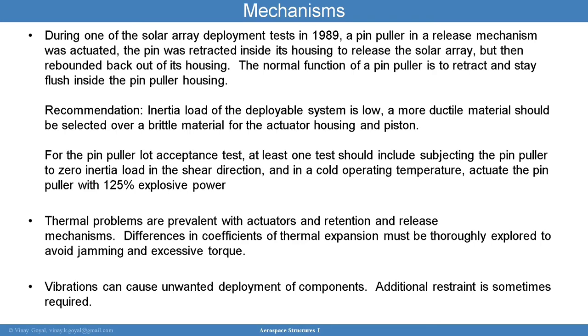During one of the solar array deployment tests in 1989, a pin puller in a release mechanism was actuated. The pin was retracted inside its housing to release the solar array, but then it rebounded back out of its housing. So it didn't stay retracted like it should. The normal function of the pin puller is to stay back, but it didn't work properly. The recommendation there is that you want to ensure the inertia load of the deployment system is low, and that a more ductile material be selected over brittle material for the actuator housing and the piston. And you should consider a pin puller lot acceptance test, because at least one test should subject the pin puller to zero inertia loads in the shear direction, and in a cold operating temperature, actuate the pin puller with 125% explosive power.